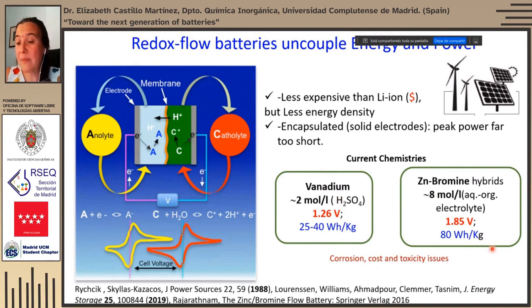The other chemistry that dominates redox flow batteries is that of zinc bromide, which reaches very large solubilities, up to 8 mol. Of course, the larger the solubility, the larger the energy density of the chemistry. So increased solubility is one of the most important aspects in redox flow batteries, along with having a large voltage difference between the reactions that occur in both electrodes. But all these chemistries have corrosion, cost, and toxicity issues.